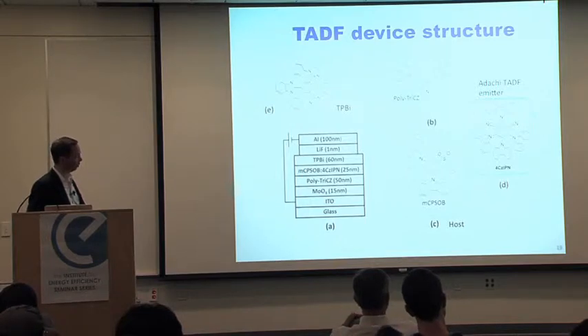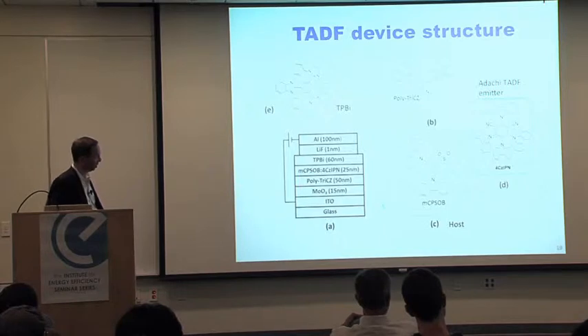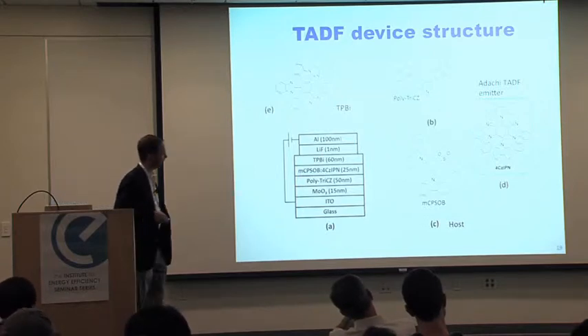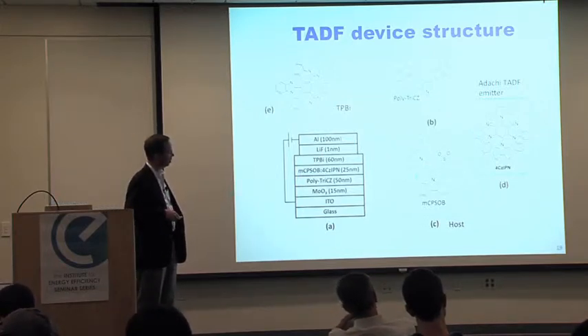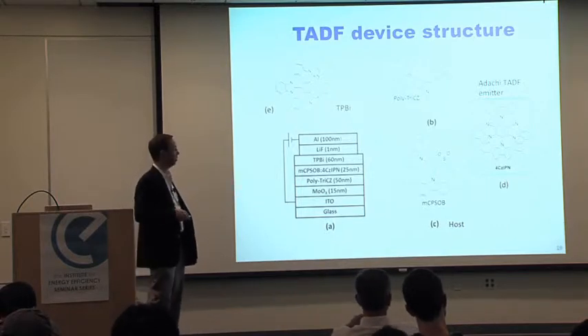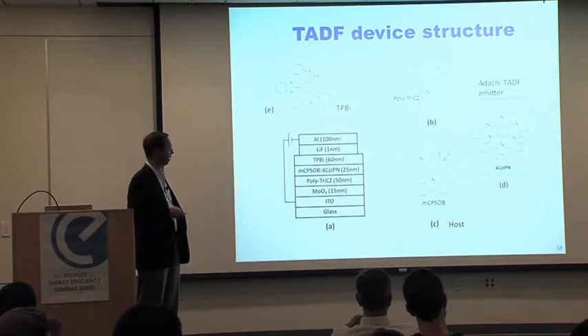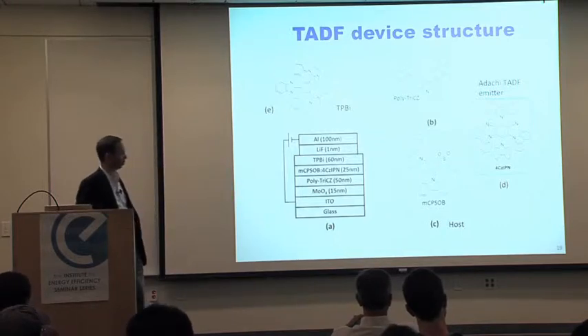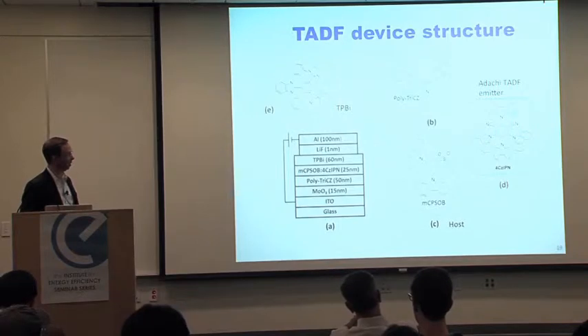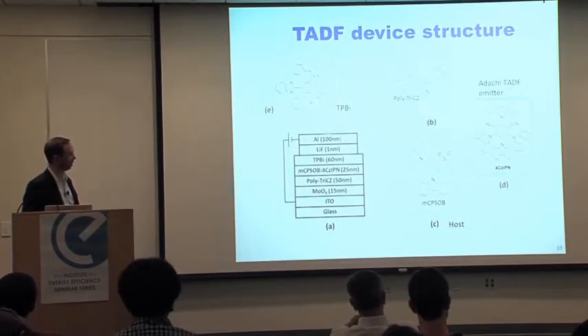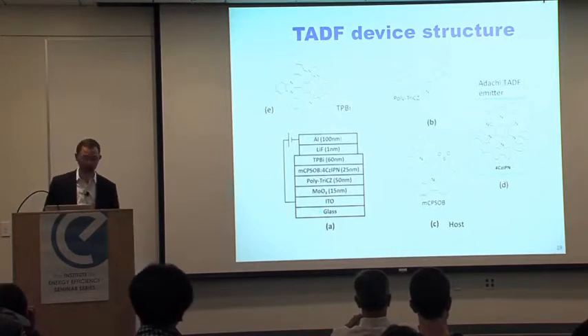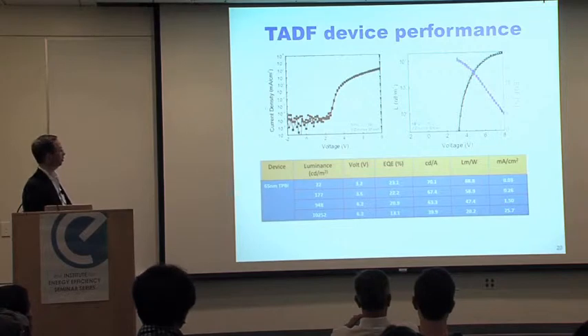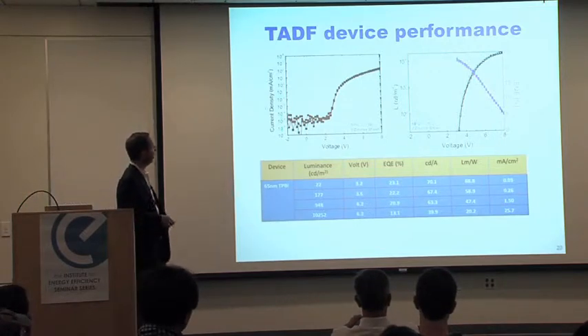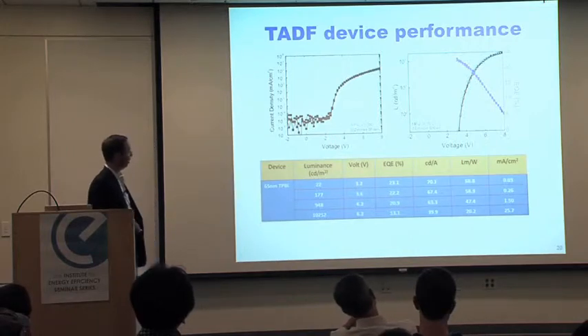And so we took one of these compounds here, and we mixed it into one of these host materials that we developed earlier. And the rationale here in the design of these molecules was, again, to get ambipolar materials that transport holes and electrons quite well. So again, we have carbazole groups here, and that sulfone group here, which has electron transport properties. And by mixing that TADF emitter into a host like this, and in a traditional device here with ITO and glass, we can get the following performance. So you can see on the left-hand side, you have the current density versus voltage. These devices turn on at fairly low voltage.